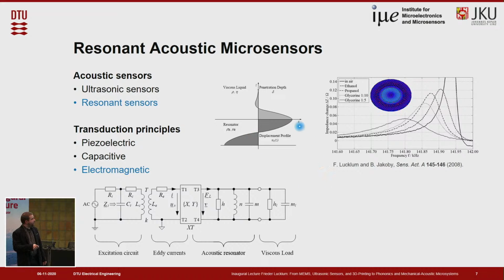And this evanescent part of the wave is very much dependent on the material properties of the medium, for example, density and viscosity. And therefore, by measuring the behavior of the resonator, by looking at this standing wave and how it changes, we can see that it results in a frequency shift and in a change of the resonance depending on what kind of liquid we have, what kind of density, what kind of viscosity this liquid has, and therefore we have a sensor to measure density and viscosity.